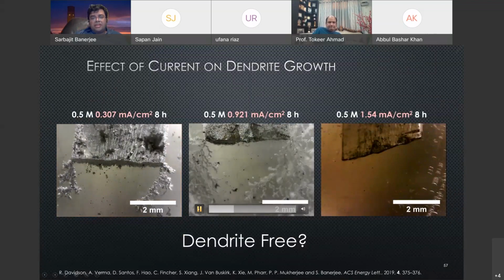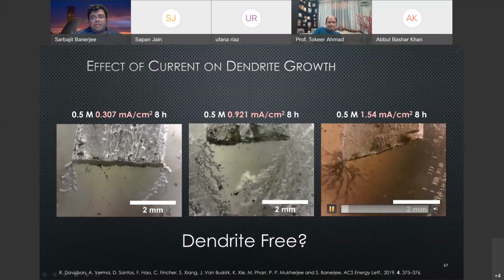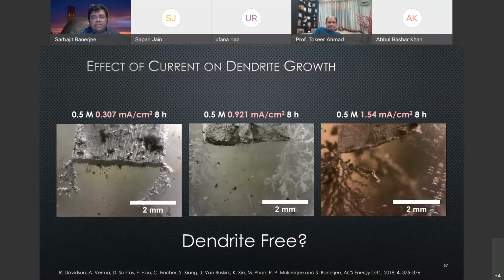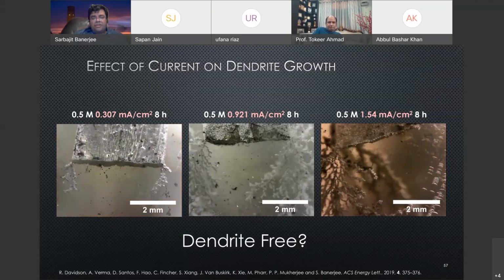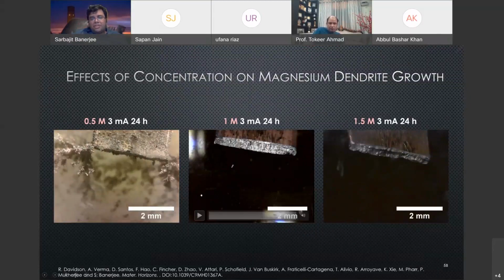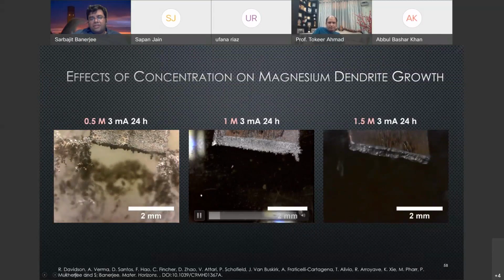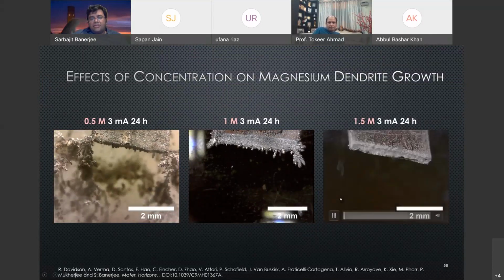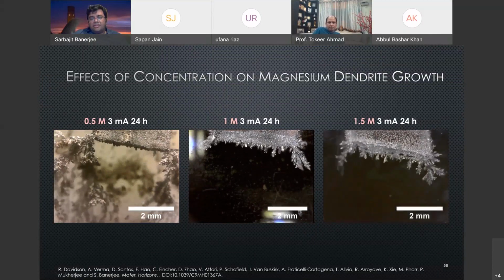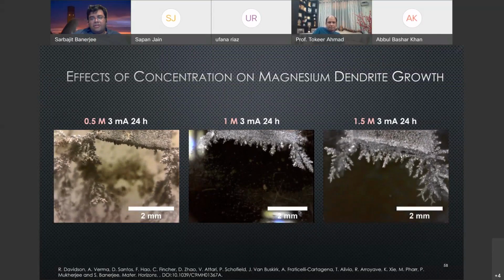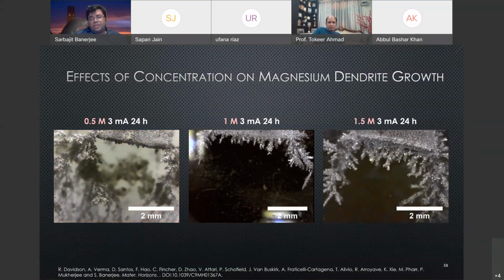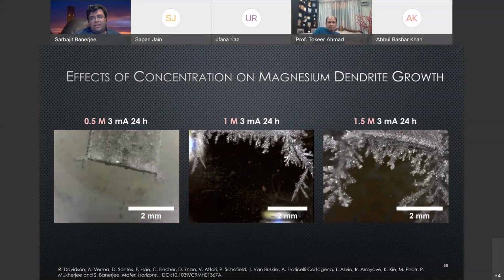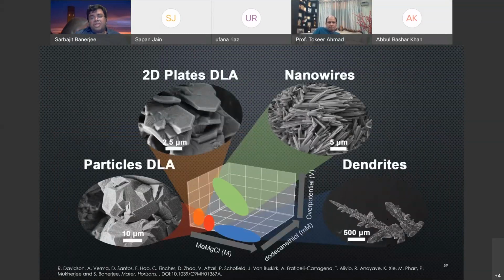Okay, so yeah, I can play these videos here, and you can see how dendrite formation changes as a function of the current density. Very quick as you increase the current, and the packing of the dendrite also changes, depending on the concentration of magnesium, at low concentrations versus intermediate concentrations, versus high concentrations. Really spreading out here. So beautiful Christmas trees, but not good news for metal anodes. Okay, so we see different regimes.